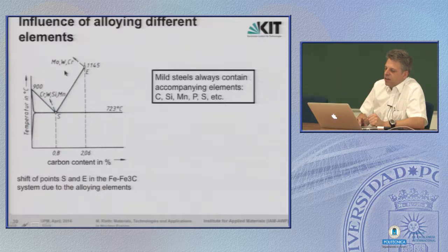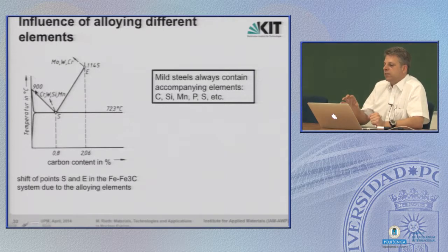Again, this is the iron carbon phase diagram, the relevant part of it. And if you add to such an alloy molybdenum, tungsten or chromium, this point, the one end of the austenitic phase is shifted in that way. Elements like chromium, tungsten, silicon, or manganese shift this point in that direction. So the effect of alloying different elements into a steel is that you in general modify the shape of the iron carbon phase diagram.